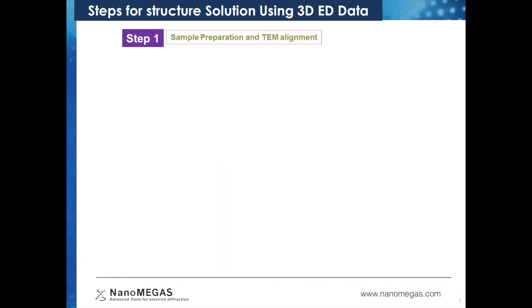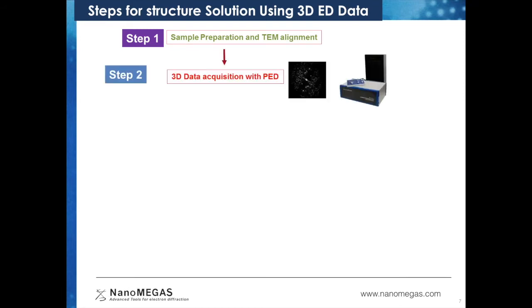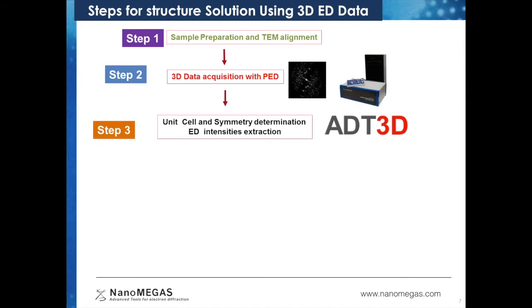First step is to do sample preparation and align the TEM for a diffraction experiment. Second step is to collect 3D precession electron diffraction data using the hardware developed by NanoMEGAS. Third step is to determine unit cell symmetry and extract intensities from the collected 3D electron diffraction data. This can be done with dedicated software like ADT3D, supported and provided by NanoMEGAS.